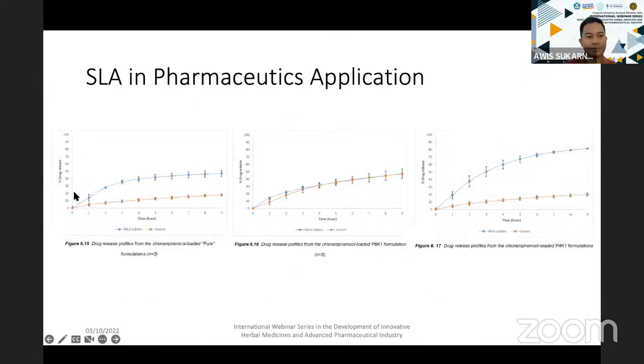And then this one is where I combine the mini tablet and the insert that I printed. You can see here that the mini tablet showed a faster release profile compared to the insert, except for the PEG 6000 here. The release profile is basically similar, slightly faster at the beginning, but after that it becomes similar, just the same release profile as the other one, whereas the mini tablet showed a higher release profile compared to the insert.